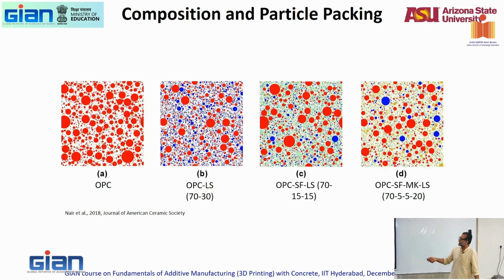I want you to look at this carefully. This is just the particle size distribution of plain cement, so all the different particles. I throw in a few more limestone into cement, right? 70% cement, 30% limestone. All these blue particles are limestone, and limestone has a smaller size distribution than cement. What happens to the packing density of this system compared to this? It's definitely going to be higher.